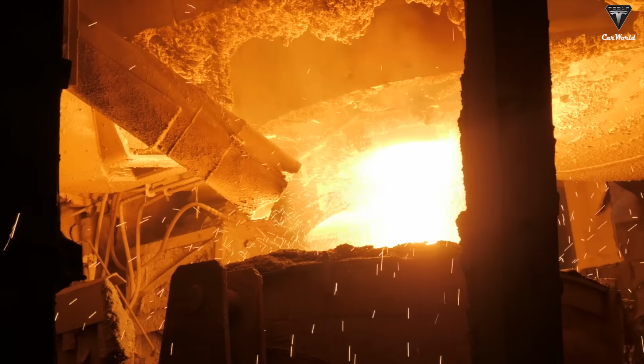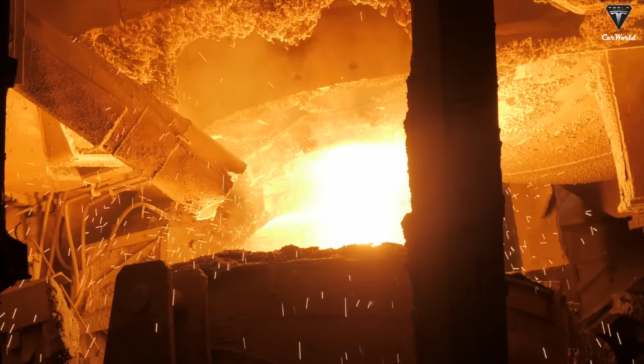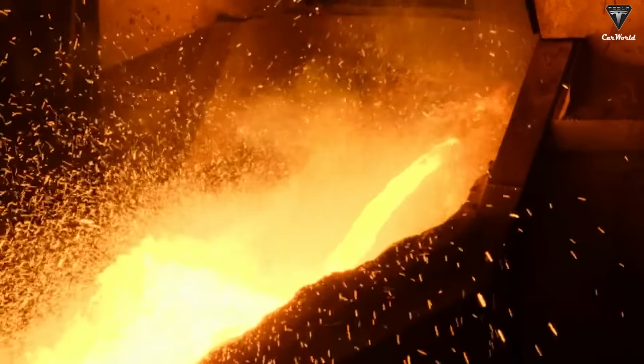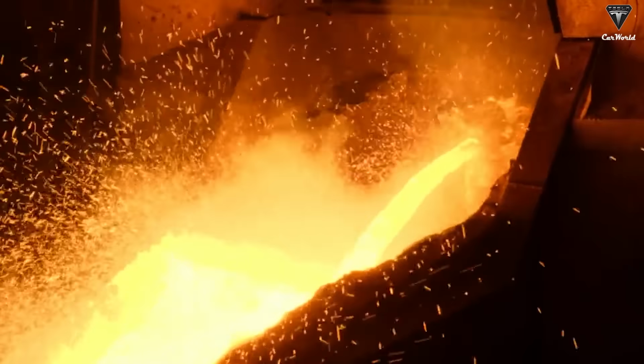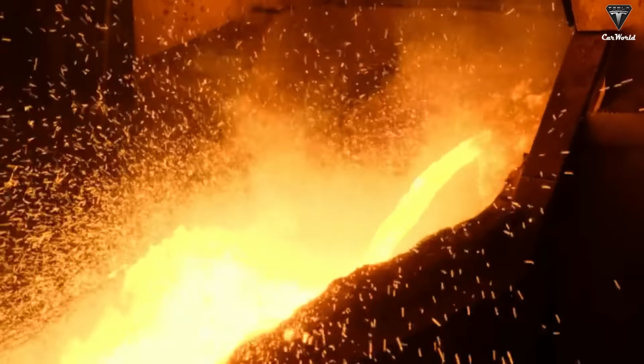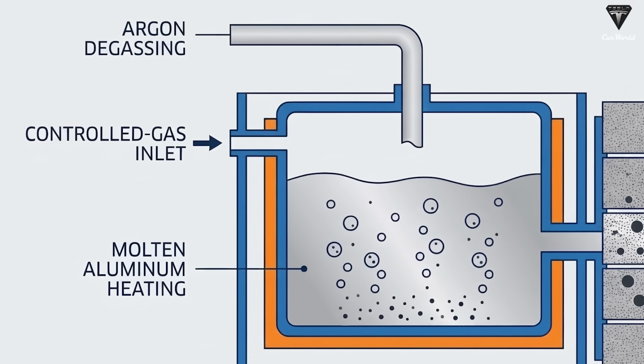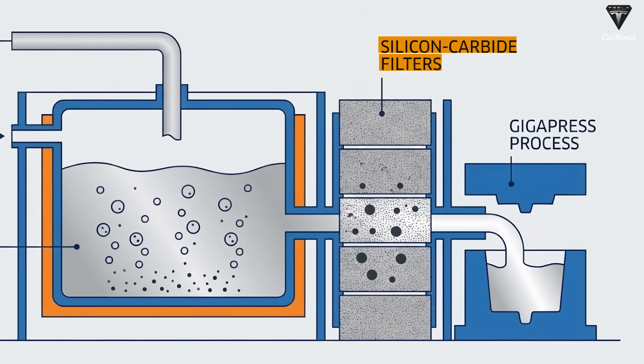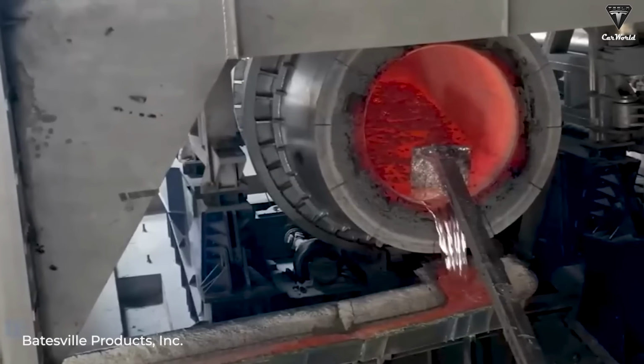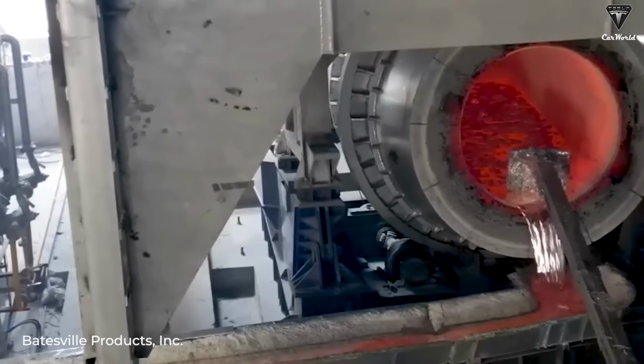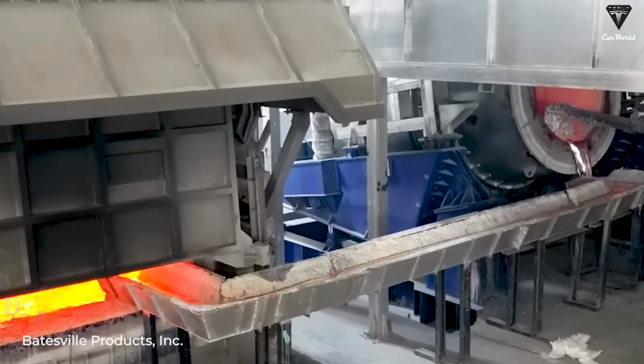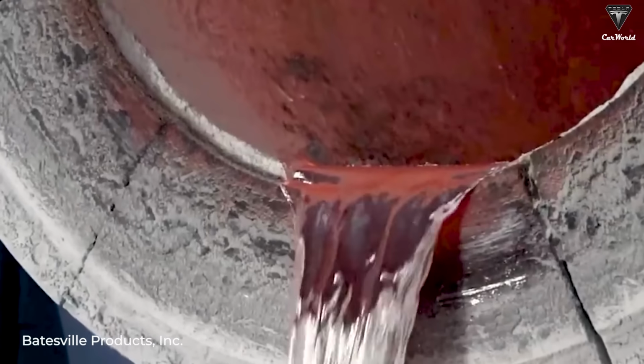But even here, Tesla still has to solve a problem that's invisible to the naked eye. Molten aluminum reacts with its surroundings and can contain trapped gases or unwanted particles. That's why the system uses a controlled gas environment, argon degassing, and silicon carbide filters to remove larger impurities. Only after the metal reaches the required level of purity is it ready to enter the most critical stage of the entire process, the casting mold.